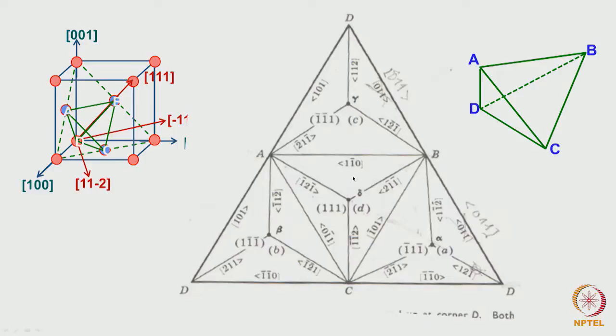This delta B is essentially the movement when we look from outside onto this layer, because there are other atoms which are going to sit on this surface and this surface as well as on this surface. The projection of an atom on this surface will be here. That will be moved from here in a direction delta B. If it is moved, that will create an intrinsic stacking fault. That is, the convention is that if we are looking into the Thompson tetrahedron from outside and displacements are being done on the atoms outside of this surface, then delta B, delta C and delta A will generate an intrinsic stacking fault.